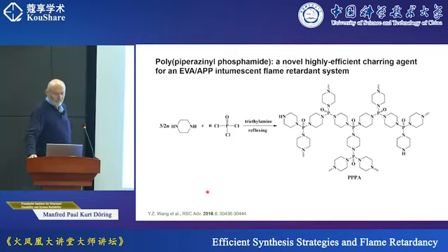Okay, piperazine itself is used in a lot of publications. Here is one by a so-called substitution reaction. That means you use a chloride and an amine as a piperazine, 2 + 3 functional groups, and you get a thermoset or a cross-linked material now between phosphorus as a phosphorus amide.